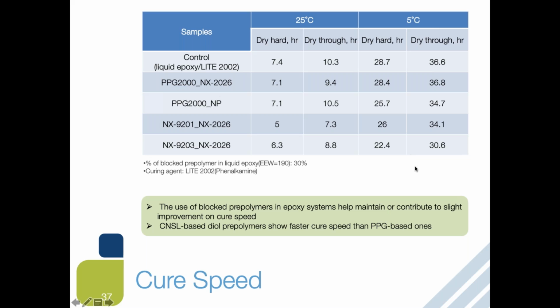So this study also ensured that when you use around 30% of this prepolymer in a 2K epoxy system, you can still achieve cure at room temperature and even at low temperature like 5 degrees C.